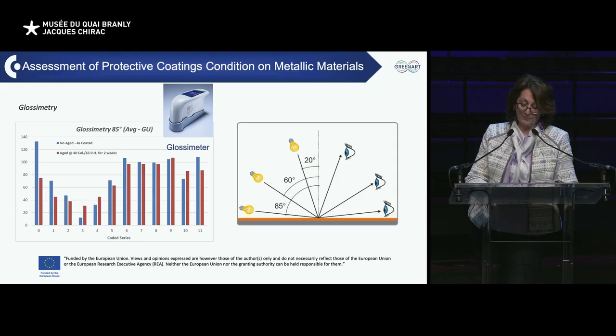This reduction in glossiness points to micro and nanostructure changes happening within the organic coating. However, it's not quite that simple. We've also observed indications that moisture absorption can temporarily increase glossiness. And it's a bit counterintuitive, right? But it seems the moisture is having a temporary smoothing effect or altering the refractive index of the surface. And then there is the extreme case, when the coating is almost completely gone, essentially disappeared.